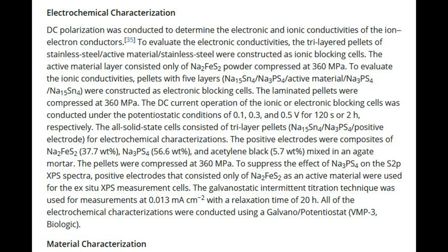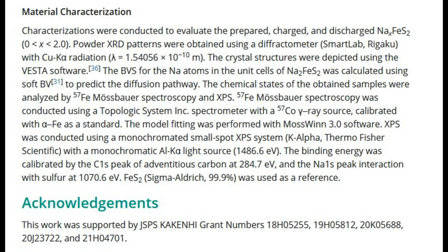Material characterization. Characterizations were conducted to evaluate the prepared, charged, and discharged NaxFeS2, 0≤x≤2.0. Powder XRD patterns were obtained using a diffractometer, SmartLab, Rigaku, with Cu Kα radiation, λ = 1.54056 × 10^-10 m. The crystal structures were depicted using the VESTA software. The BVS for the Na atoms in the unit cells of Na2FeS2 was calculated using softBV to predict the diffusion pathway. The chemical states of the obtained samples were analyzed by 57Fe Mössbauer spectroscopy and XPS.